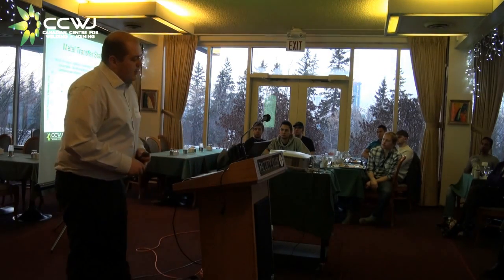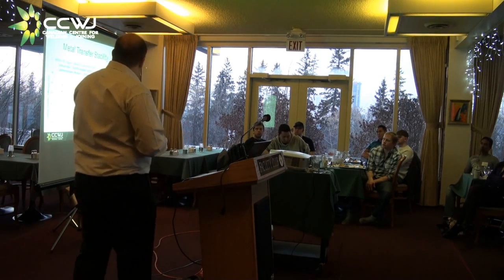Well, what we found is actually dropping it down gives us better results. We get to maintain more carbide in the weld pool. This consumable, we started with 35 volume percent. It has more stable transfer because it has a thicker sheath than the thin sheath cousins. And after welding, we have about 29% in our weld. Or we're losing 20%. One fifth of the carbide we just bought at $1,000 a spool or whatever they are has now been lost. It didn't end up in our weld, and that's a big deal.